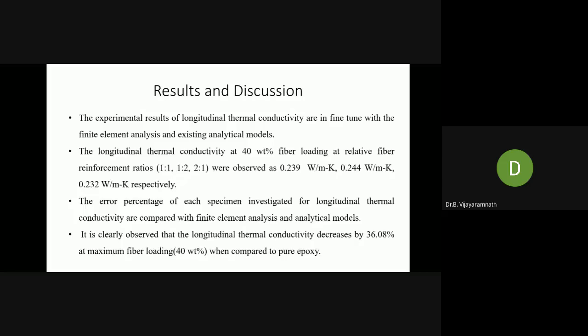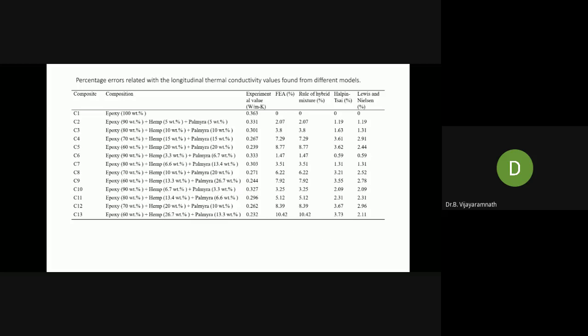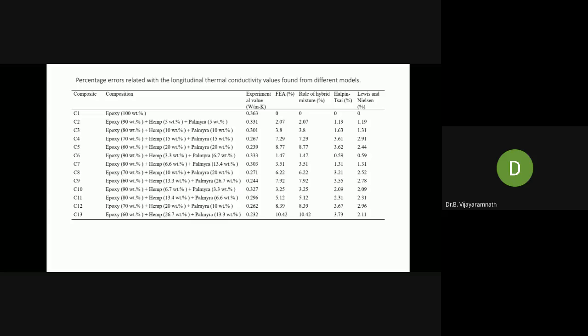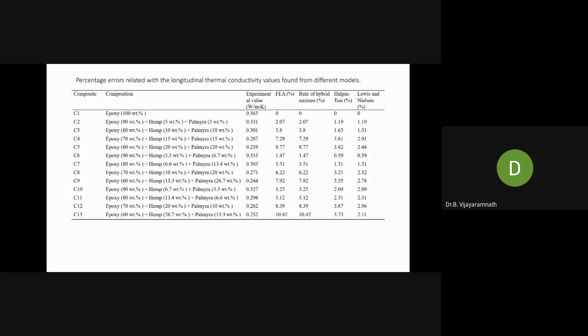So this is the table that gives clarity on the comparative statement for the error percentage. The first column represents the experimental value. The next one is the finite element analysis. The next one is the rule of hybrid mixtures. Next, we use the Halpin-Tsai model and the Lewis and Nielsen model. Out of which, at a weight percentage of 40, the lowest thermal conductivity observed was 0.232.